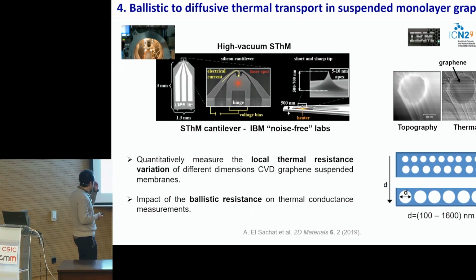In this case, what we wanted to see is how the heat dissipation changes by increasing the graphene lateral size. We want to see any crossover from ballistic to diffusive thermal transport in these graphene flakes. How we did this: we grew graphene with CVD, and then transferred it onto silicon dioxide, creating suspended graphene with different diameters. We want to see the impact on the ballistic resistance or the thermal conductance measurements. So in this case, we use our probe, our tip, as a heat source.